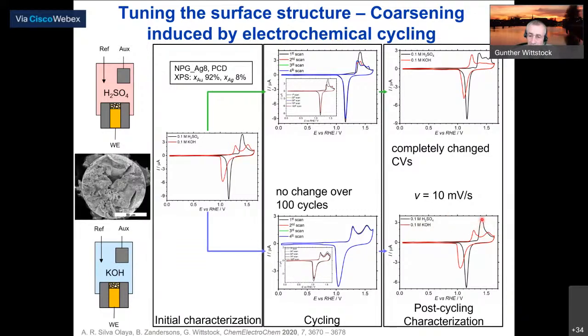We have this big peak, and then the second scan, this is gone and looks like this. Yeah, if we continue in potassium hydroxide, of course, it stays the same. If we then transfer this sample, which was pre-cycled in sulfuric acid, to potassium hydroxide solution, then we get something which looks completely different than what we get if we go immediately to potassium hydroxide, and we see this